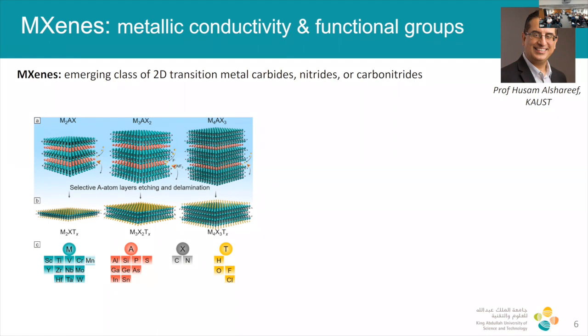And essentially what it is, it's represented by this formula, right? M subscript n+1, X subscript n, T subscript x. Where M is a transition metal, any one of those. Typically, it's titanium. X is carbon or nitrogen, and T represents the surface functional group. The surface functional group can be hydroxyl groups, oxygen, fluorine, and chlorine.